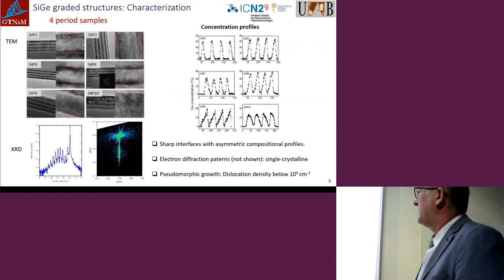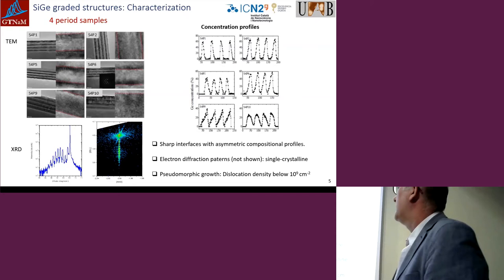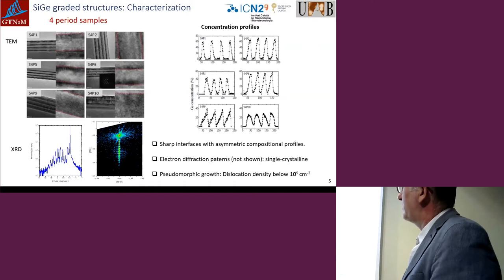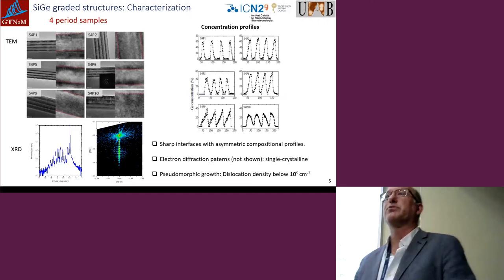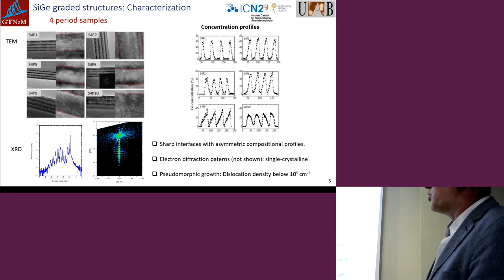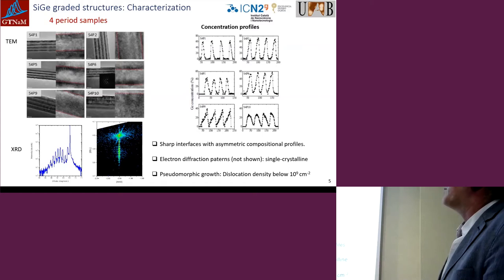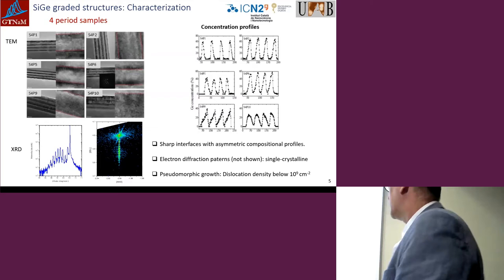We see this by the fringes that we have in the high resolution X-ray diffraction pattern. And we have been able, by doing TEM, to map the concentration profiles. And this is quite important for the analysis that we'll be doing later. You see that these profiles are anisotropic. That basically means that one side of the interface is different from the other side of the interface. And we have different types of profiles that might, in principle, impact differently the value of the thermal conductivity in our sample. So basically, we can say that we have sharp interfaces with asymmetric compositional profiles,